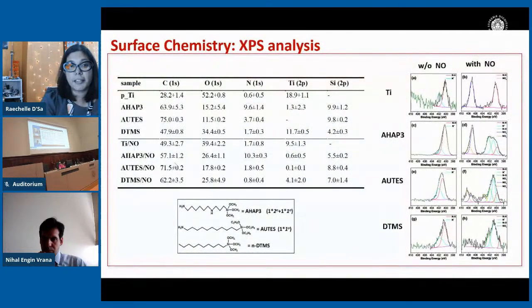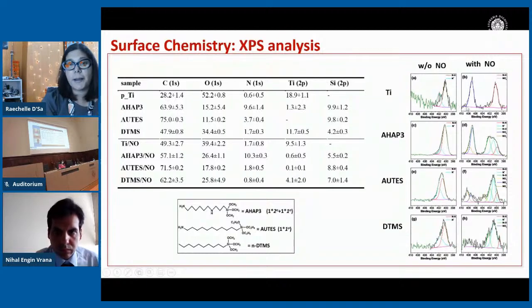We then followed the surface chemistry after silanization and the formation of the diazeniumdiolate onto the surface. You can observe that the silane has added to the surface by an increase in the nitrogen concentration of the surface, and likewise for the diazeniumdiolated surfaces. If we look at the high resolution XPS spectra for the two silane surfaces that are capable of forming the diazeniumdiolate, we confirm the presence of the diazeniumdiolate because of the peaks at higher binding energies that are associated with the N-O bond that is formed with the diazeniumdiolate.